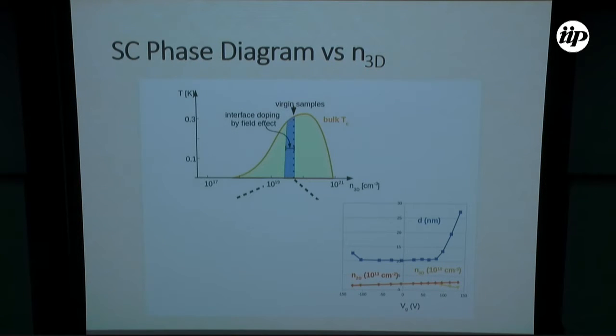And so if we now plot our TC as a function of the 3D carrier density, the one in yellow, this is what we obtain: TC versus the 3D carrier density. We see TC is going up, down, and then coming back as the 3D carrier density is decreased by the deconfinement of the gas. And what you see is that TC is not even a function of just the 3D carrier density, but there is some other parameter that we need to take into account to explain why for the same carrier density we obtain two different TCs.